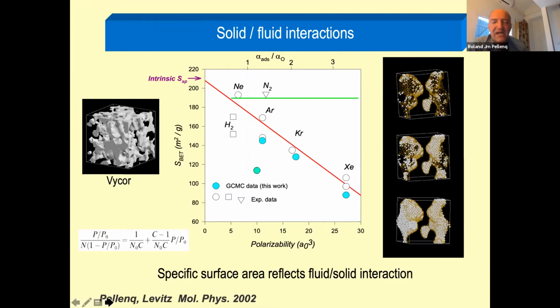It turns out there is a linear dependence of the specific surface area, this geometric quantity measured by everyone, as a function of a specific property called polarizability. In this case it's very simple, because when you write the interaction of those rare gases with the surface, this is the only term that attracts molecules to the surface. This is called dispersion interaction, also known as van der Waals interaction, proportional to the polarizability of the interacting molecules. So you see that if you do the adsorption of xenon, you get half of what is measured by argon for the same substrate.